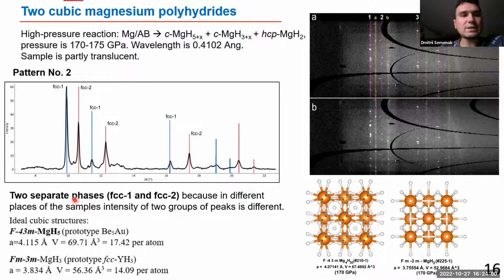And those phases are separated because in different places of the sample, we saw that one phase almost completely disappears. So we are sure that those are two different compounds. And the simplest explanation is that those two compounds are cubic ideal magnesium H5, prototype beryllium 5 gold, and the predicted cubic magnesium H3, Fm3m magnesium H3, prototype yttrium H3. So that was the simplest explanation,